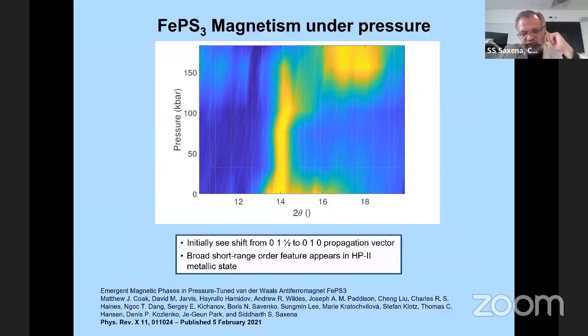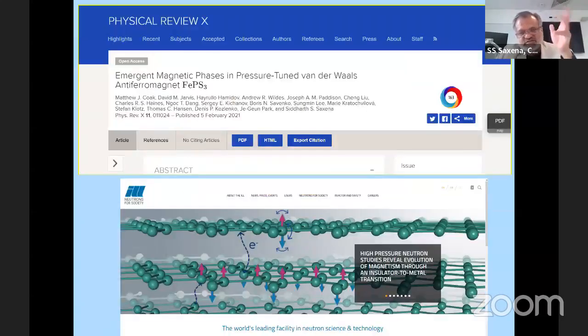We studied the magnetism using probably the first high pressure neutron experiments to these kinds of pressures, where we could actually follow the wave vector and look at the broad short range features which appear in this HP2 range, and mix into this new kind of magnetic metal. More details to be discussed here. This was very much liked by the ILL, where we did this experiment for the first time. So we developed, together with people who have done this work in the past and developed this technique, like Stefan Klotz and colleagues, from lab-based high pressure to neutron-based high pressure.